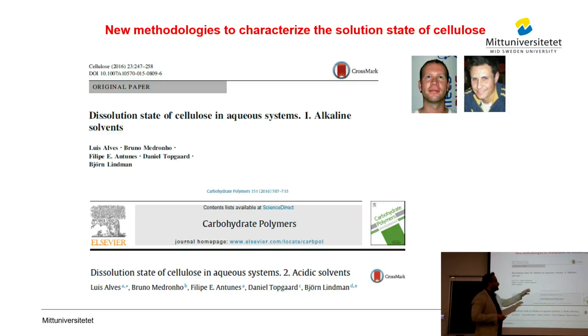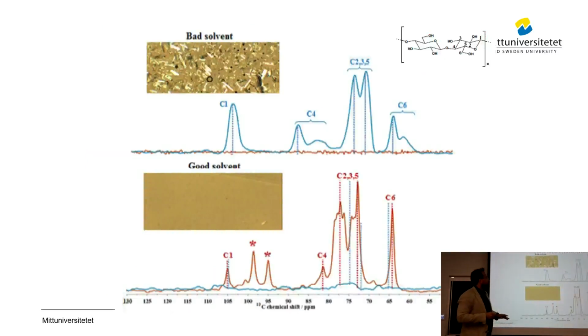And we have done some work together, essentially with Daniel Topgaard from Lund University, a key guy for NMR methodologies. So we were looking at alkaline and acidic solvents. And the idea here, using some of his approaches, solid state NMR, I don't know too much about the technical details, but essentially, if we have a bad solvent with this technique, we would only see the blue signal, so the solid contribution of the signal. If we have a really good solvent, we would see the red signal, let's say the liquid contribution. And based on that, we could quantify how much material was dissolved or not. We could do spectroscopy because we also have the peak position. I mean, it's a very powerful technique that was not used before in cellulose, and we have introduced it to the cellulose world.